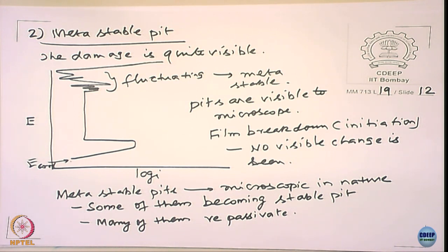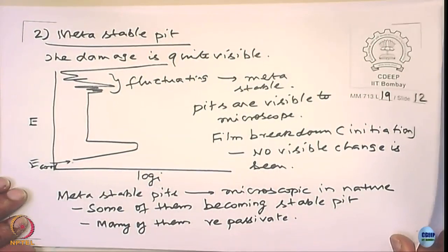So, the concept of saying that E pit corresponds to pit initiation is not the right terminology to use. All we can say is that yes, the pit will start stabilizing at that particular potential. Okay, am I clear? So this is something very important to look at. In fact, this has led to the concept of what is called induction time.